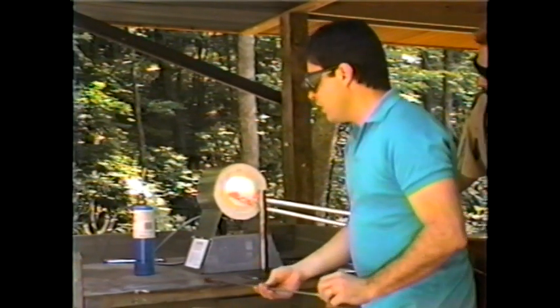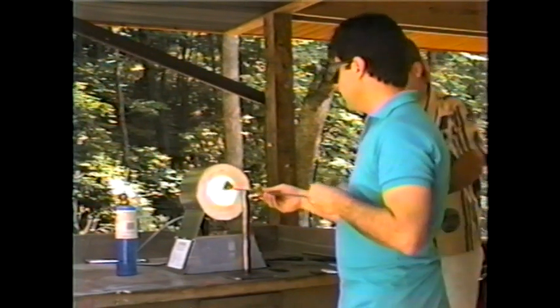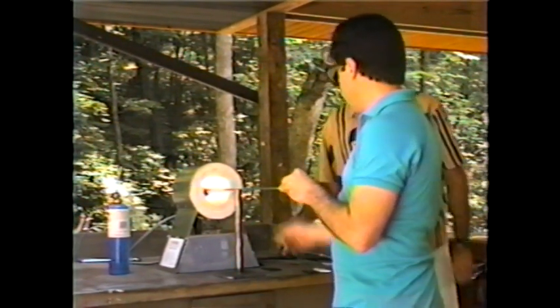Important that I try and not let this punty get too hot, or we'll have a temperature difference between the two glasses, and this glass will want to flow a lot more than the new piece. There we go. Great. Go ahead and get a white hot. Get this one hot. Piece of white.